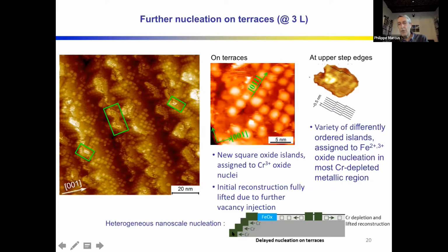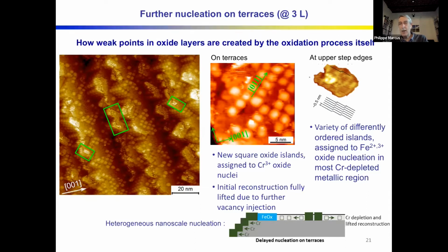At the beginning, we have formation of chromium oxide. So we have depletion of chromium in this area, and that's where iron oxide will then form just because the chromium concentration has been decreased. And we believe that these areas will be weak points for the corrosion protection by a surface oxide. I should conclude there that this is the way the weak points are created by the oxidation process itself.